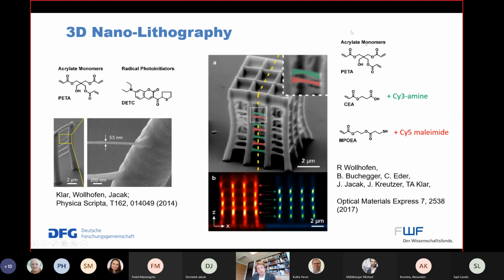We usually use acrylates, acrylate monomers, and the gray here is our favorite triple acrylate molecule. Then we can use that acrylate molecule and mix in a few carboxy groups, and we write every second bar here, and then we change the resist. The new resist contains acrylate groups and thiol groups, and we write every other second bar. Then we can use amine or maleimide molecules to have covalent bonds to the thiols or to the carboxys. And we see that we can successfully modify these bars with 3 different polymers in 3 dimensions.